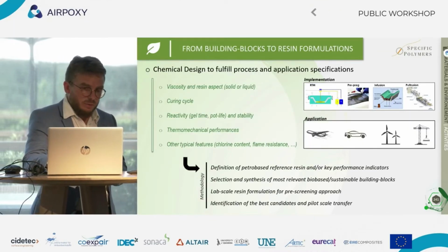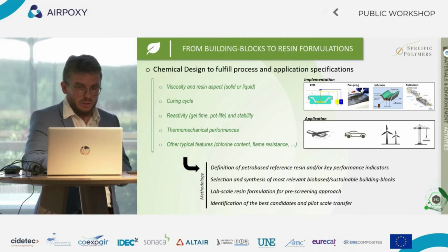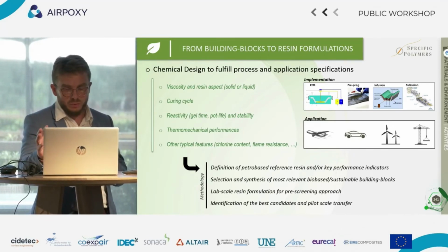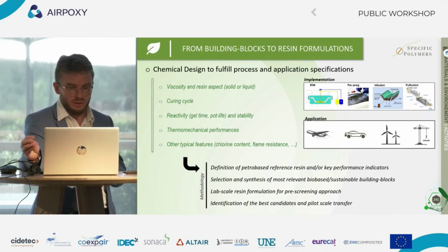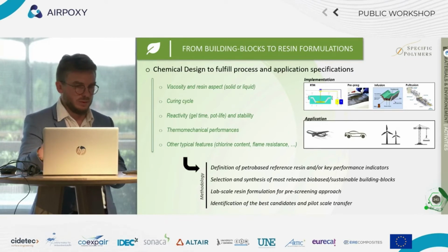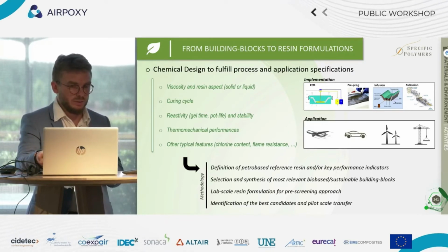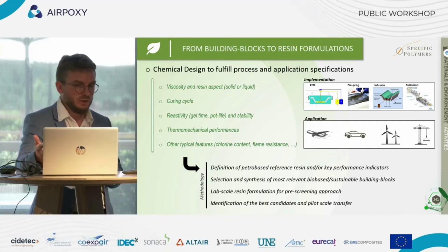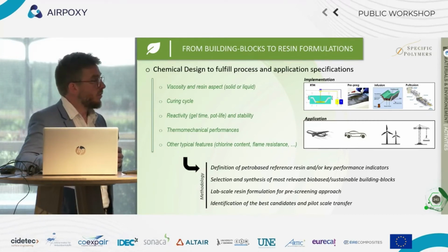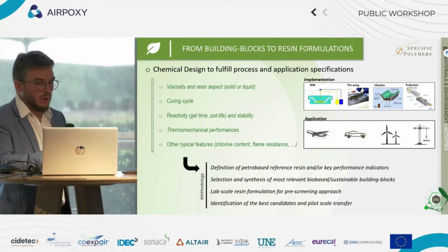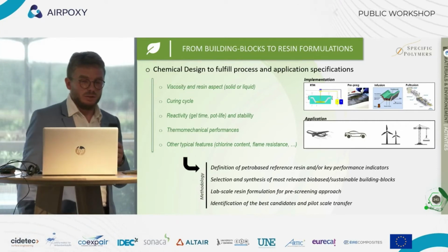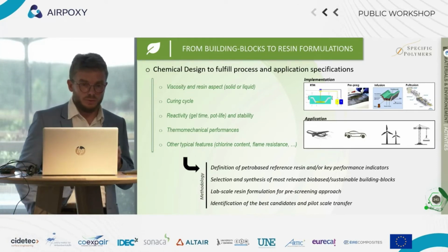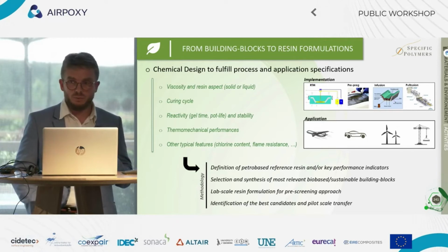How do we design our formulation? So as I explained already, we need to define the specifications that are linked to the implementation process and the main performances that need to be reached when the material is cured. So it's aspects like viscosity of the resin, the curing cycle, the reactivity, gel time, pot life, what the thermomechanical performances are, and maybe in some cases you have some other properties that you want to add.